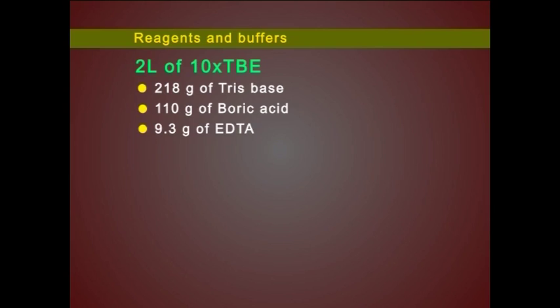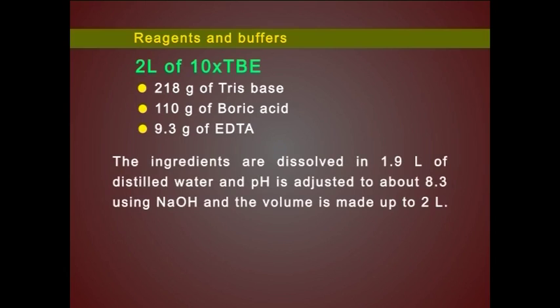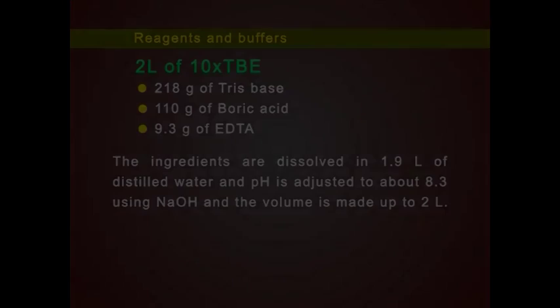Next, let us see the reagents and buffers. First is 2 liters of 10x TBE buffer. For this, 218 grams of Tris base, 110 grams of boric acid, and 9.3 grams of EDTA are required. The ingredients are dissolved in 1.9 liters of distilled water, and the pH is adjusted to about 8.3 using sodium hydroxide, and the volume is made up to 2 liters.